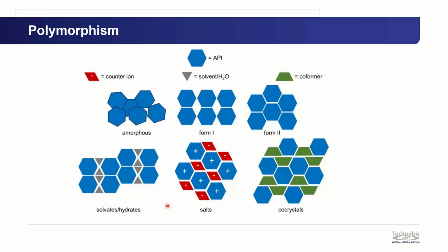And describing polymorphism can be done based on the internal crystal structure. So in amorphous solids, what you have is a lack of long-range order, so the molecules are more just packed together rather loosely. For polymorphism, you can have different packings of the same API within the crystal lattice, giving remarkably different physical chemical properties. If you introduce a second component, which is a solvent or water, you form solvates or hydrates. This is where the liquid is incorporated into the crystal structure and stabilizes the lattice.